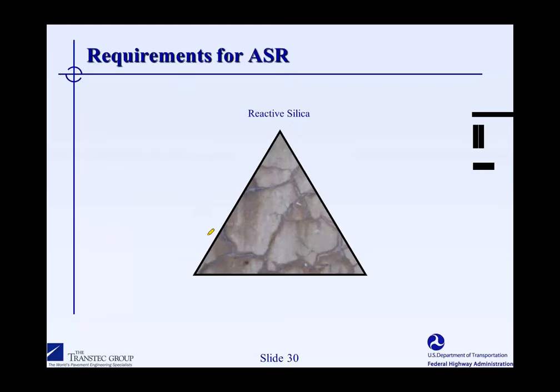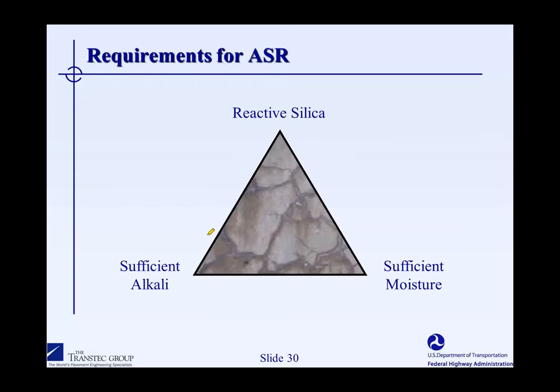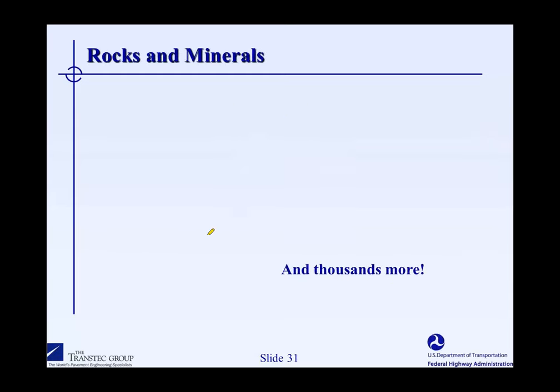Okay, so having learned a little bit about the mechanisms of ASR, we can see what the three main ingredients are that we need. We need a source of reactive silica, which will be provided by the aggregate. Oh, I'm sorry, I jumped forwards a little bit there. We need a sufficient supply of alkali, which is provided predominantly by the cement, and we need a supply of moisture, generally more than the moisture that's originally mixed in with the concrete. We need some external source of moisture as well to get significant ASR to occur.